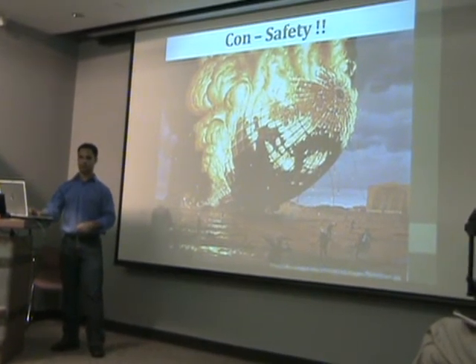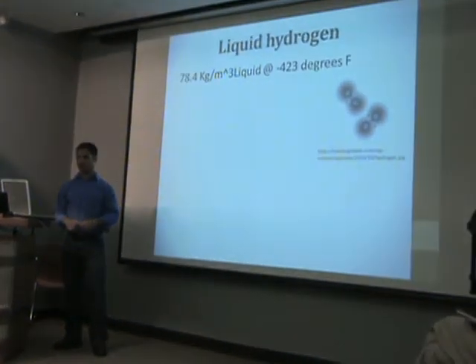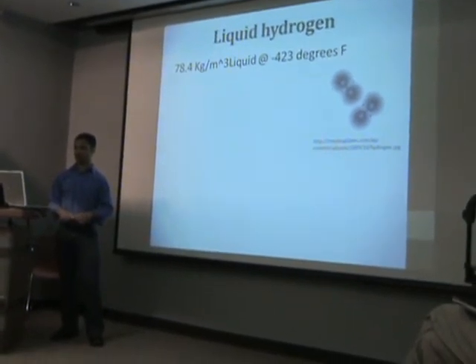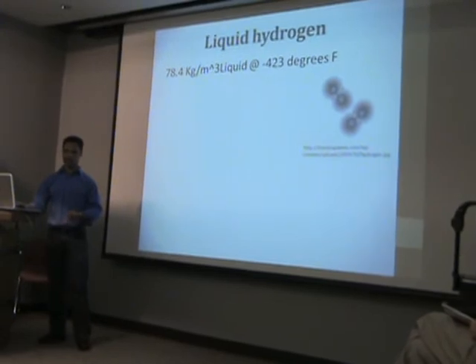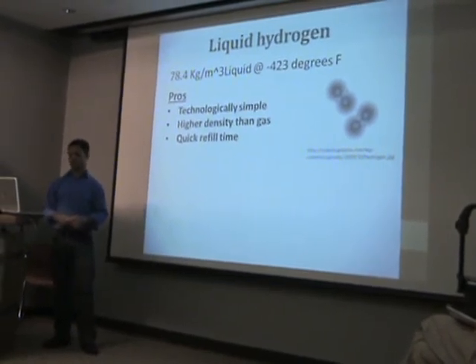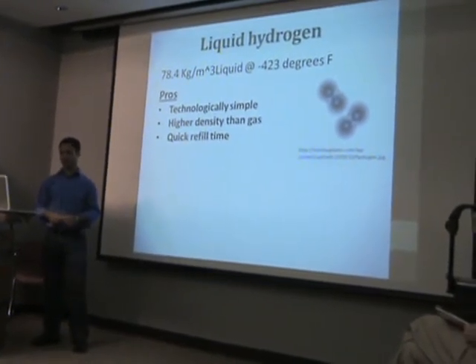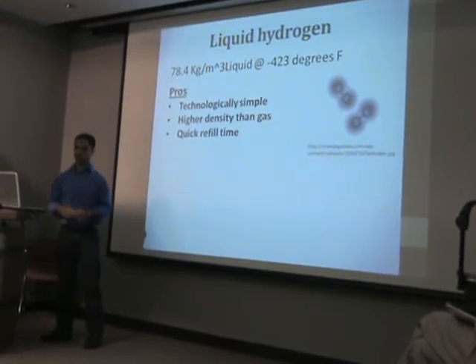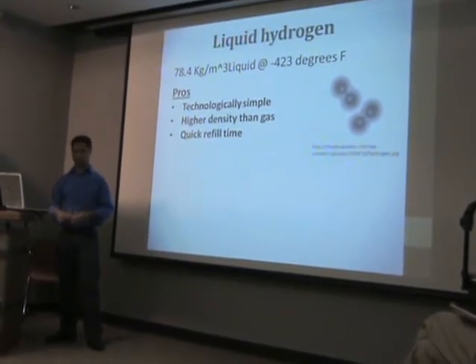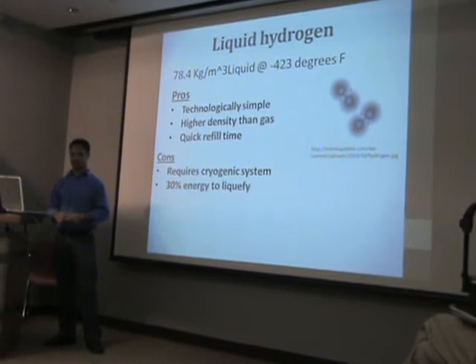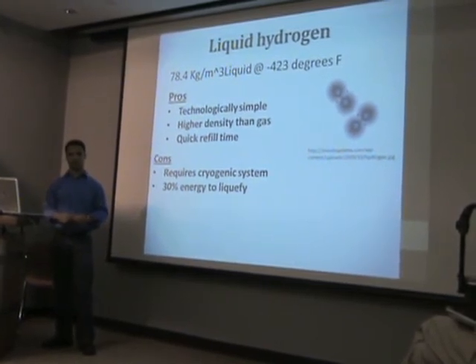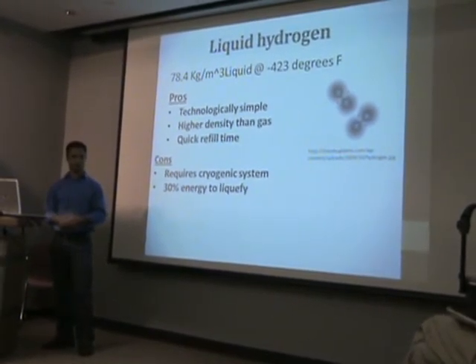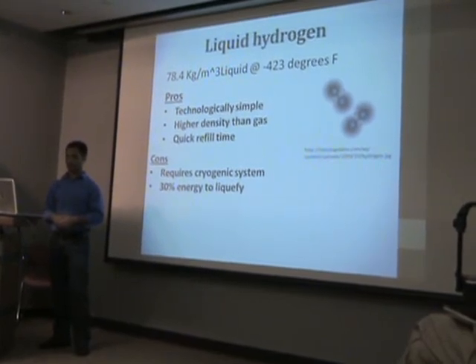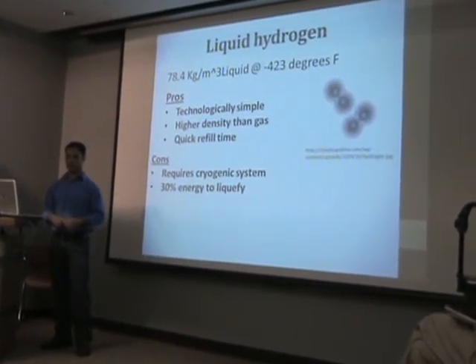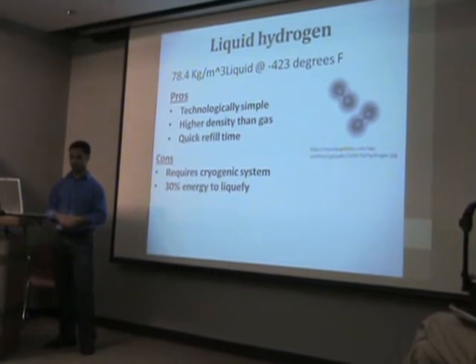The next method on the list was liquefied hydrogen. Has a density of about just under 80 kilograms per cubic meter, stored at a little under 20 degrees Kelvin. Has some very strong positives. It's technologically simple to liquefy hydrogen. It has a higher density than the hydrogen compressed gas and a quick refill time. However, it does have some drawbacks of its own. The cryogenic system required to store the hydrogen can be quite cumbersome, can be problematic, heavy, and it takes about 30% of the energy content of the hydrogen just to liquefy it.